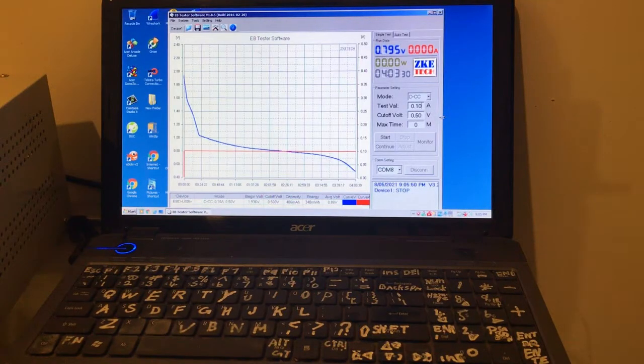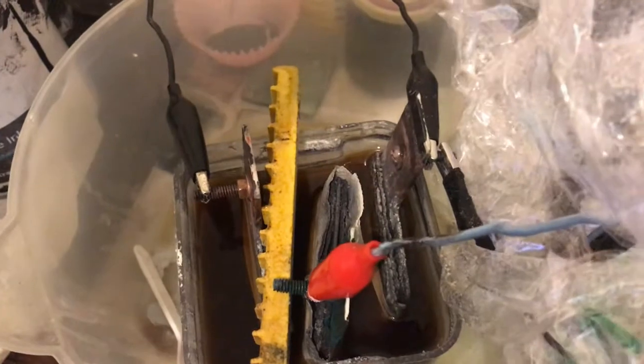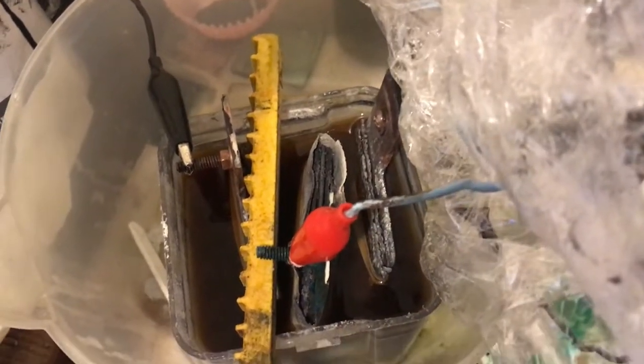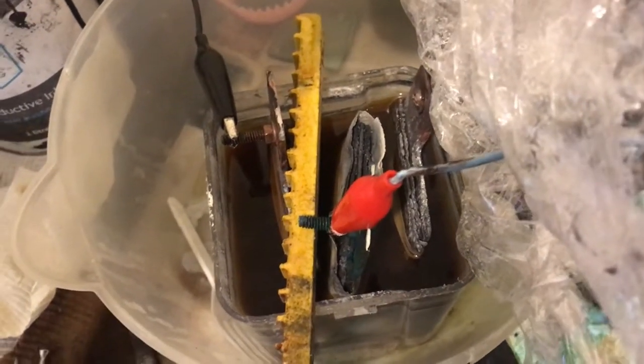This is the 22nd run of the cell for its 4 hour runtime, 406 milliamp hours, 348 milliwatt hours with an 8 hour charge, and the cells are just spread out like that, not really close to each other. We could probably get better performance if we move them closer, but that's good enough for a test.